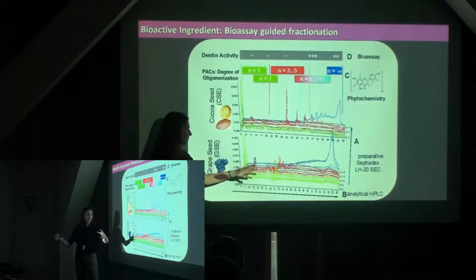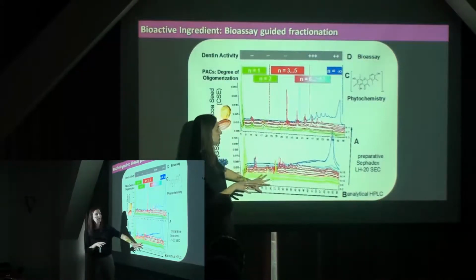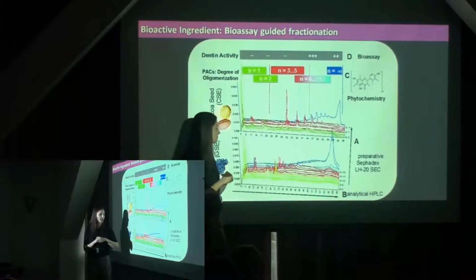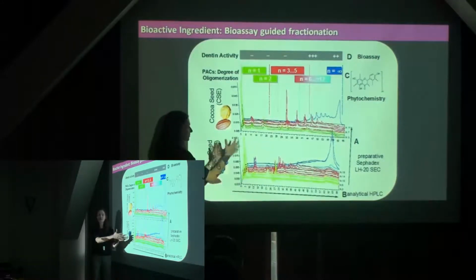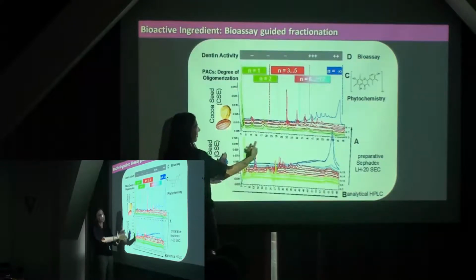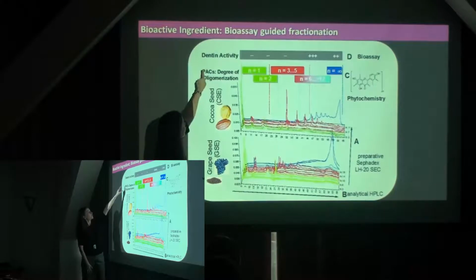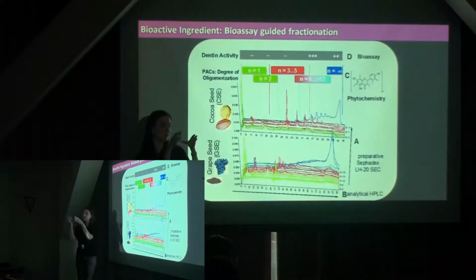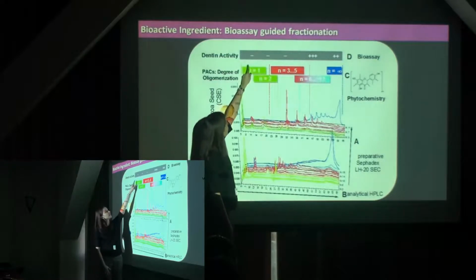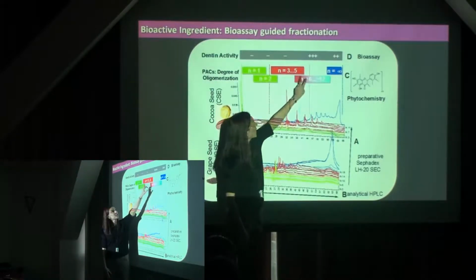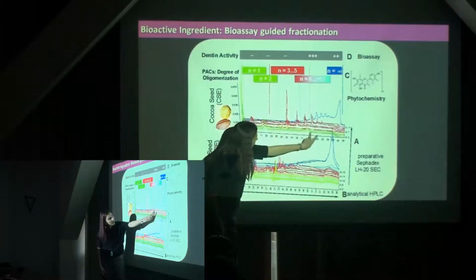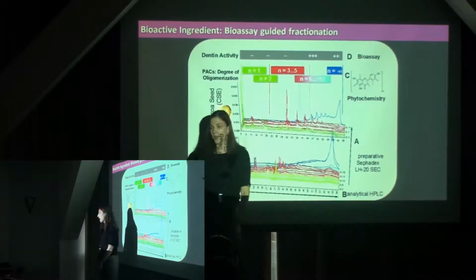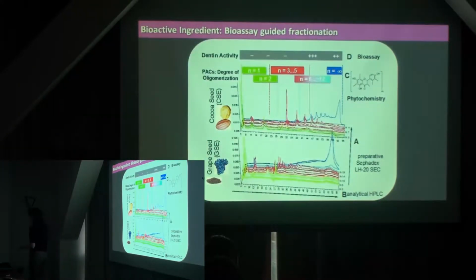We do a fractionation on Sephadex, and then we go to an HPLC, and they look at the degree of polymerization. So you have catechins, the simplest, which are monomers. You have dimers, trimers, and you go all the way. The dentin activity is a bioassay where we use this stiffness method for the mechanical properties. I don't get any activity, I don't get negative, and we start getting a lot of activity around this area, which is the higher molecular weight content, what they call oligomeric proanthocyanidins. Of course, they're the hardest ones to work with, and that's how we figured out that people haven't worked with them before, but for a reason.